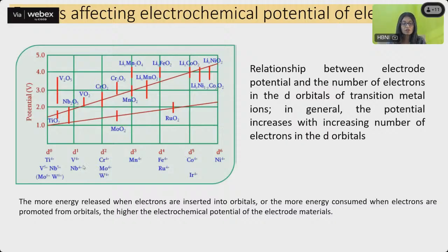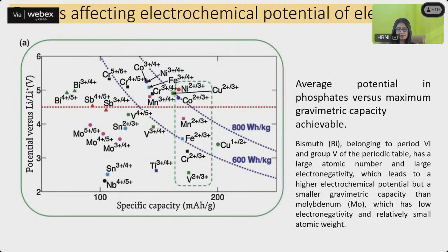So what you find is that when Professor Goodenough proposed lithium cobalt oxide in his lab, all different studies were done using these different transition metal ions, and it was found that lithium cobalt oxide was the most suitable candidate, obviously because of the potential which it was giving, and then it was gradually correlated to the number of d electrons these particular transition metal ions have.